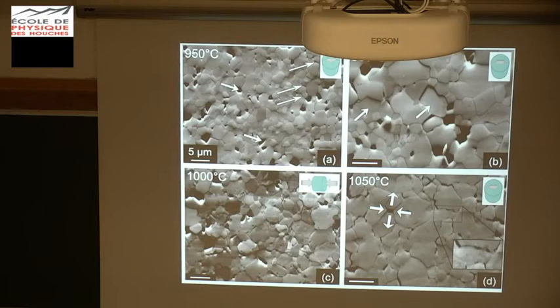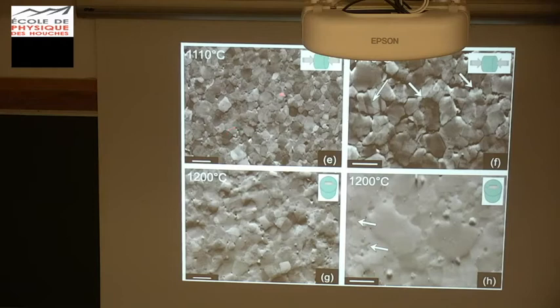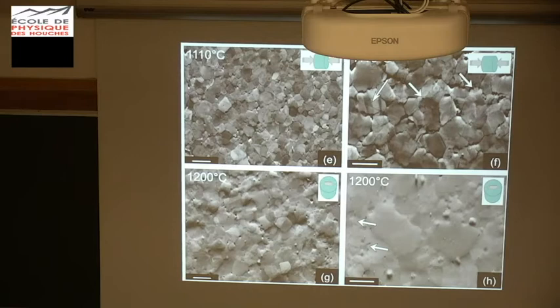Up to now, to describe grain boundary sliding in olivine, we only had cartoons. This is a nice example that it is happening, at least in my lab. As we increase temperature, the texture changes a little bit — it seems to be more dense at 1100°C. We also see, even in the backscatter images, some substructure appearing. We still have gaps — things to really prove that grains have slid relative to one another.